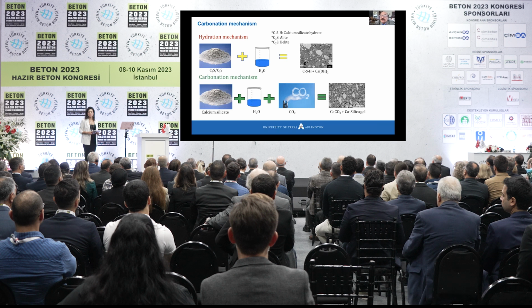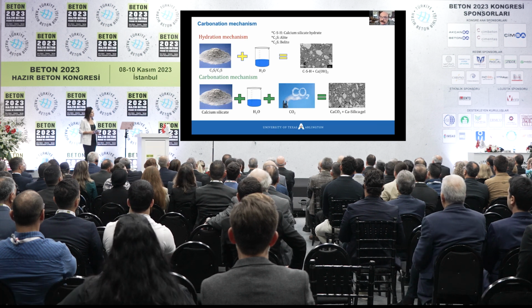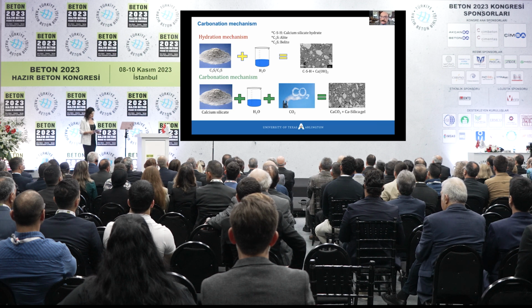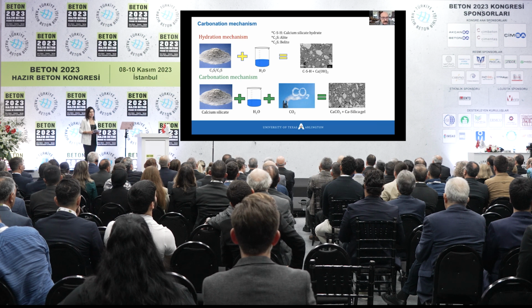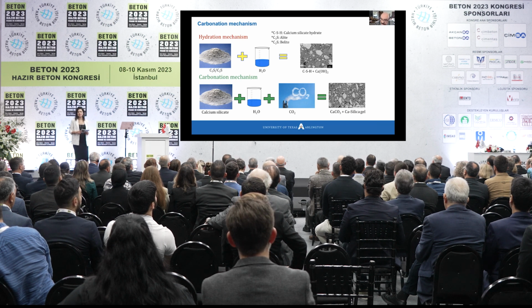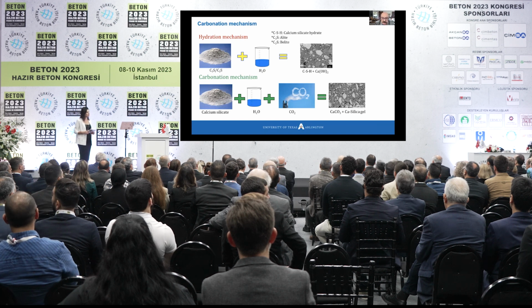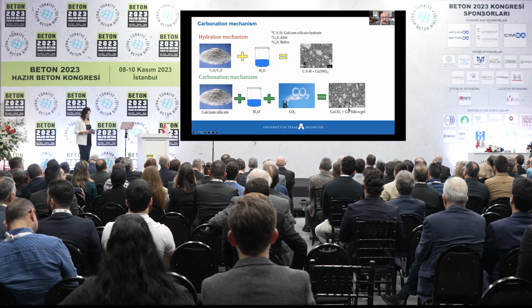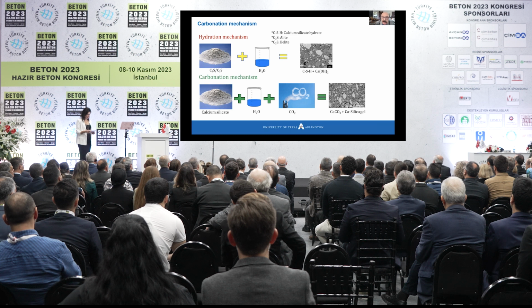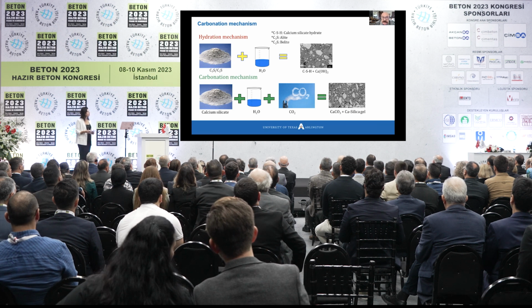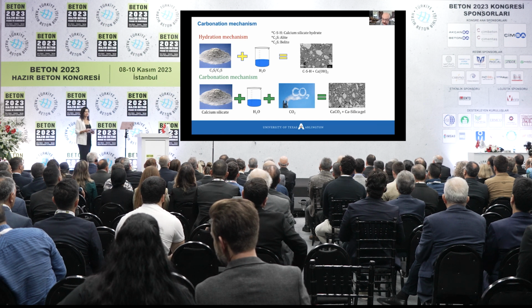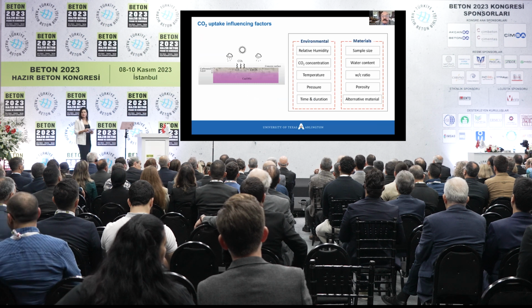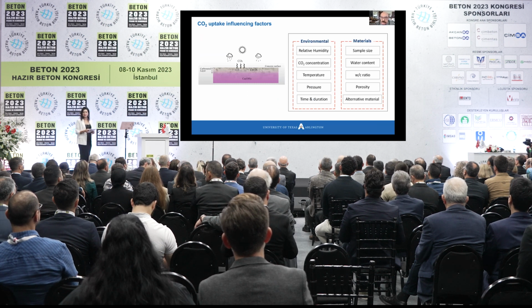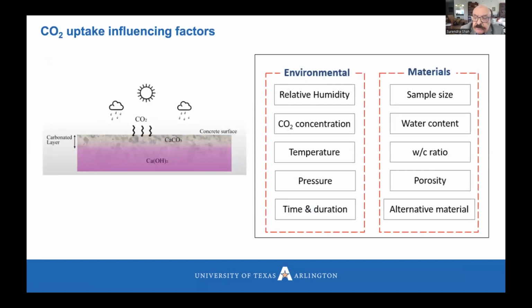If you look at this, during carbonation of cement during hydration, there are two mechanisms going on. One is the hydration of cement, as shown here on the top, and the other is the carbonation. And carbonation produces two products, calcium carbonate and, very important, calcium silica gel. How to manipulate them, both reactions and controlling the coupling, is a key thing. Now, how much CO2 we can absorb depends on the environmental factors such as temperature and pressure, CO2 concentration, and the material factors such as alternative materials that can enhance CO2 capture.